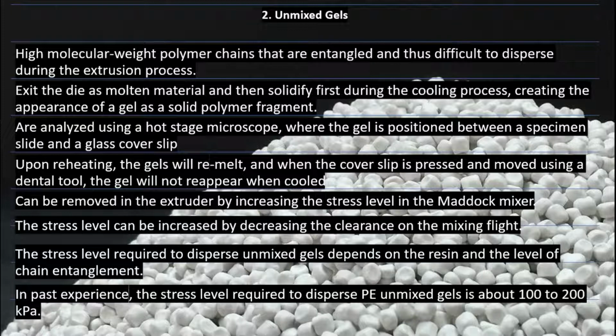Other than that, the stress level can be increased by decreasing the clearance of the mixing flight. So the stress level required to disperse these unmixed gels will depend on the resin and the level of chain entanglement. And it's actually advisable that the mixing flight should be adjusted. And so this is also a problem that is highly related to the design of the extruder.